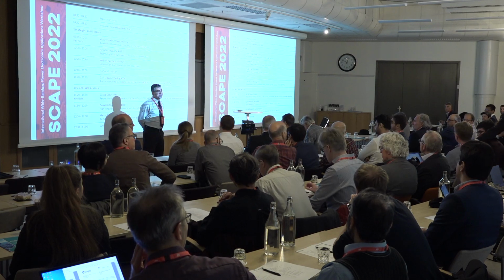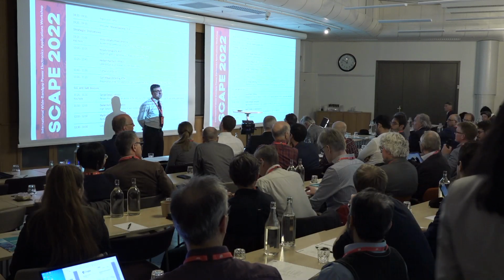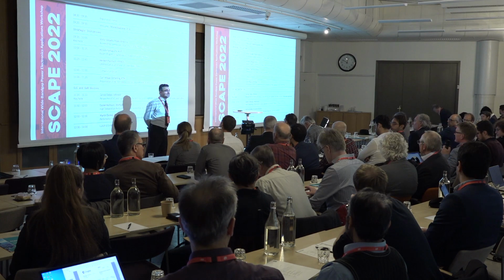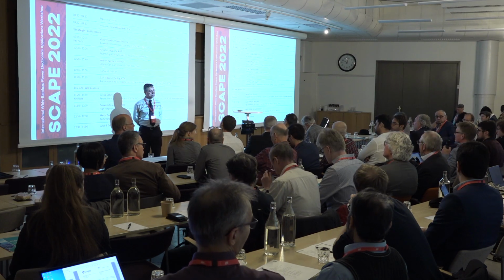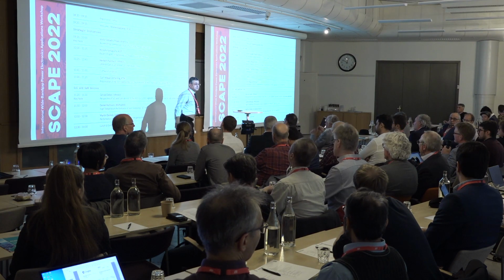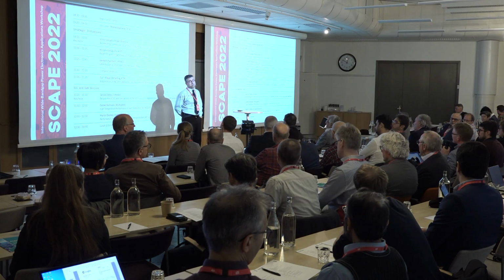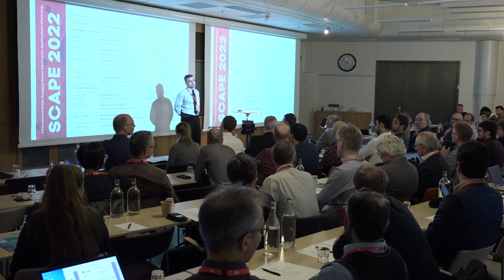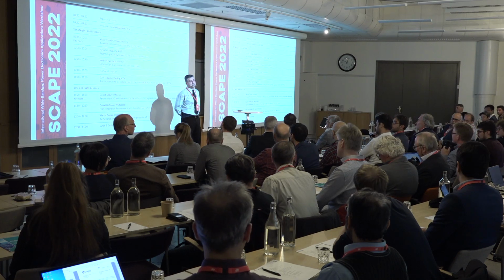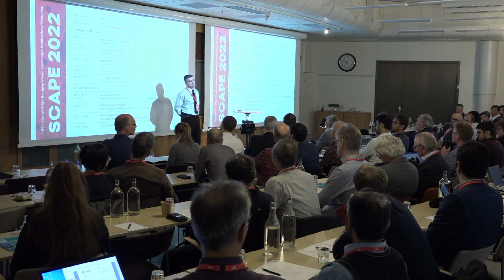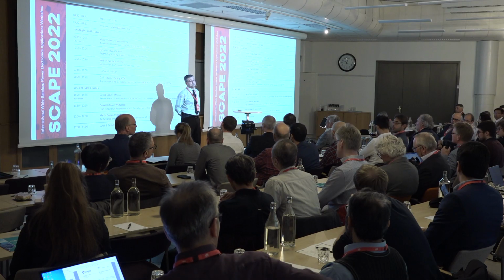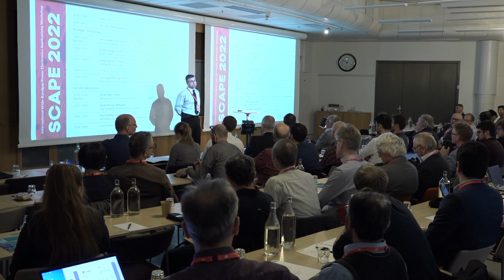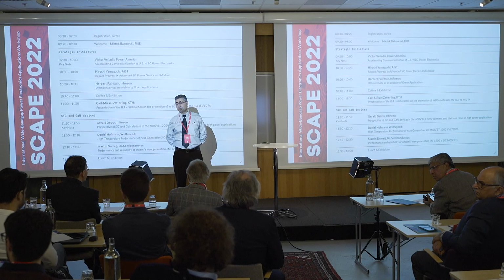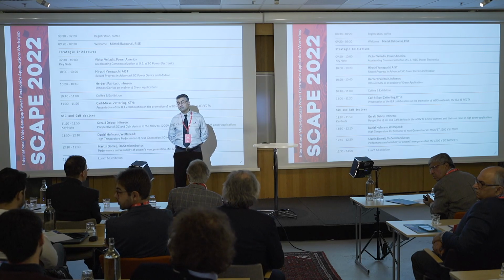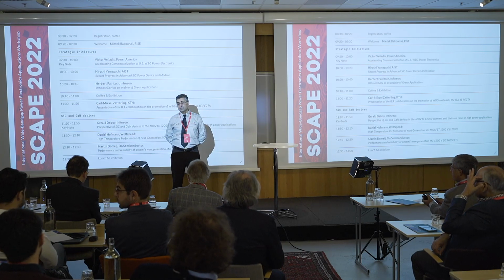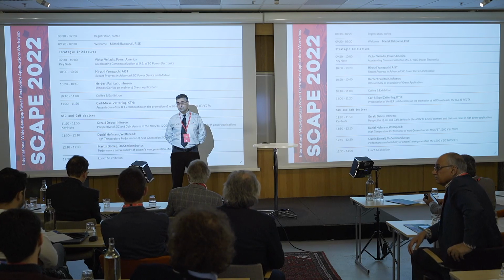Simon, this is Simon Price from Exawatt. You mentioned figuring out the value of silicon carbide and wide bandgap power devices. One of the issues that we identified a few years ago was that although the cost of silicon carbide devices is much higher than silicon, not only in PV, but especially in electric vehicles, it really doesn't matter that much because the impact on the system efficiency is so great that you can more than compensate for that increased cost with a decreased cost of the battery pack for a given range.